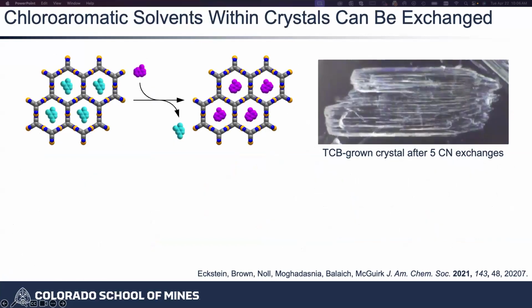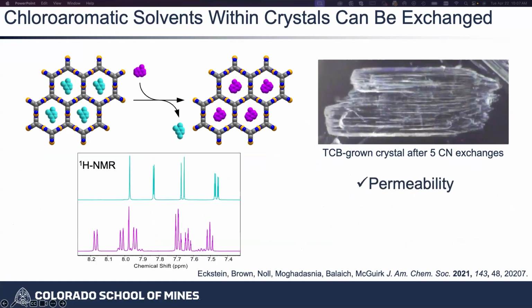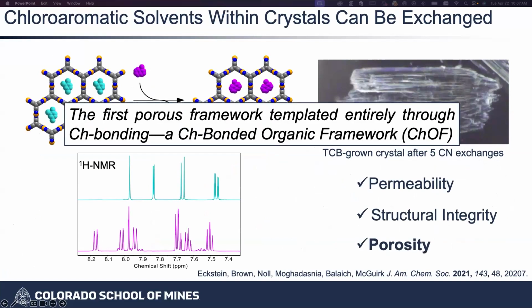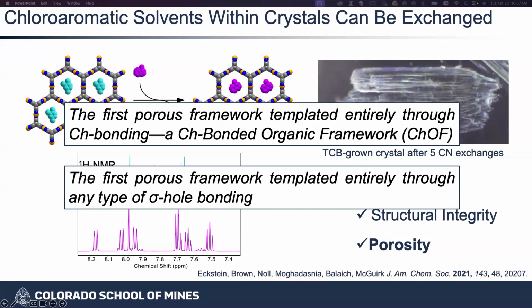Okay, so there is the starter solvent in those pores, but we were able to show that you could basically move the solvent through. We can move the solvent, and the single crystals were staying intact. We would recollect the data after changing out the solvent, then dissolve them, show by NMR that the solvent was changed, structure was intact. And so these systems were by definition porous. And so this was the first ever example of any of these sigma hole bonding interactions exhibiting porosity, and crystallography was critical to this. And so we were really excited about it.